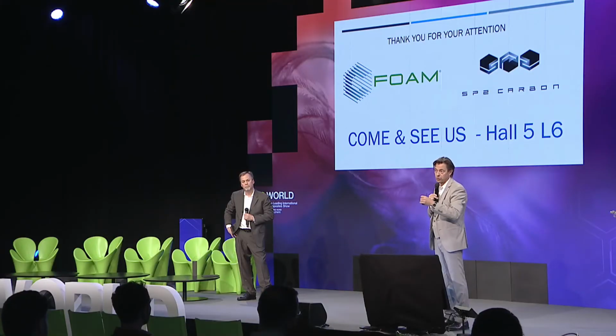Just two more numbers. When it comes to electrical conductivity and shielding, we're talking about 1 to 2% of carbon content. And on thermal, we're talking about 5 to 15%. The filler loading in a master batch or in a final compound for thermal is typically 50, 55% of filler. So there's a point where you don't really know: are you getting a filler where the resin is basically the glue, or are you still getting the resin that you chose in the first place because of performance, whether it's polypropylene, polyamide, epoxy, phenolic, etc.? So it's a significant step forward, but on the thermal, there still needs to be additional work done.